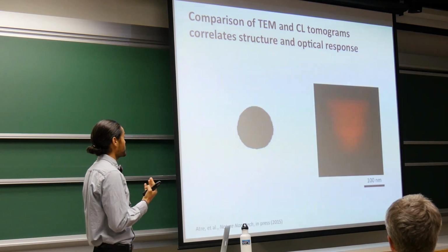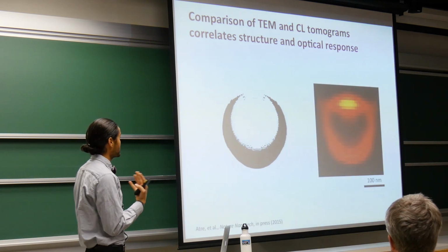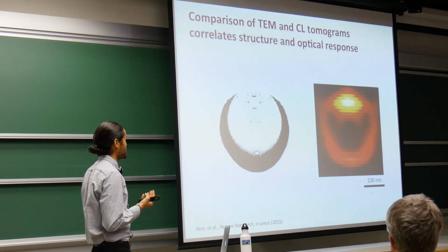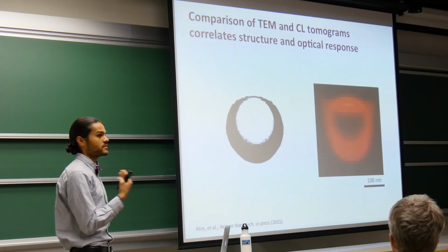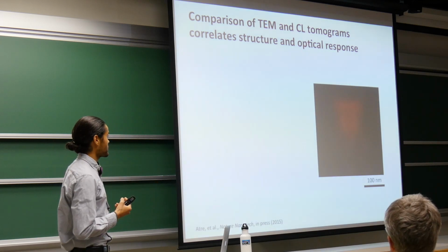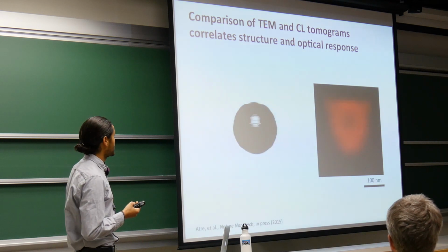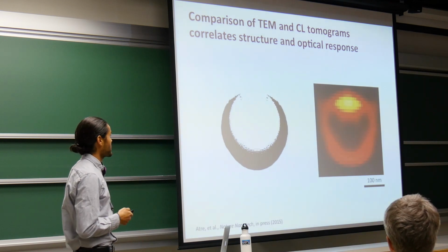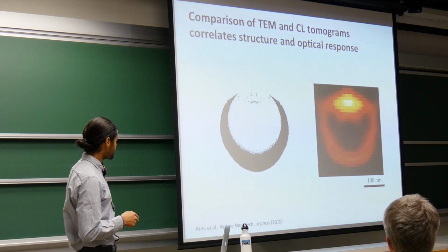So as we fly through, you can see how at first we can only see the material luminescence in the shell, but when it goes to that center point of the crescent structure, we can see a really strong resonance, the plasmonic resonance at the tips of the structure.